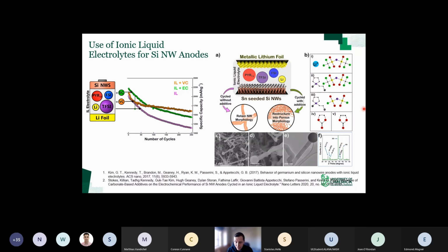So modeling, not in our paper, but in other papers, shows that Li+, so lithium ions, have a weaker electrostatic interaction with the FSI anion than they do with the TFSI anion. Therefore, it favors desolvation if they're solvated by FSI. So that lowers the energetic barrier to charge transfer. So we had a couple of interesting papers on that.